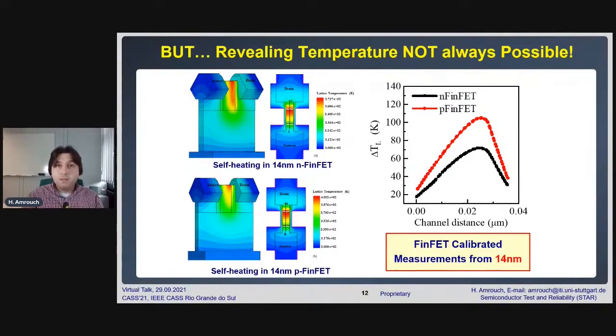When it comes to advanced transistors, such as what we see here, the FinFET transistors, the current density and the power density inside the channel of the transistor itself become very high, which means that even though you measure the temperature of your silicon substrate, of your silicon die, and that temperature still looks relatively cool or cold, the temperature inside your transistor channel is so high, but it's so encapsulated, so trapped inside your transistor, that it's very difficult to escape to the outside and then be captured. And that means your transistor is almost heating up from inside, but you cannot even observe or measure that. Your sensors inside the chip still tell you the temperature is cold.